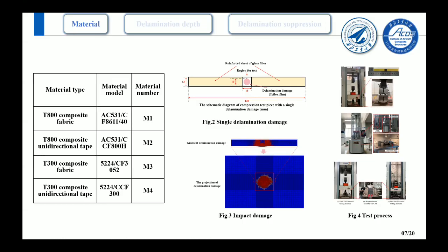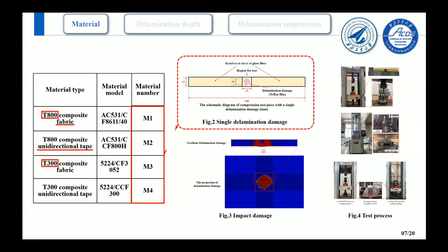For the first part of our study, we selected four distinct materials combining two strength grades and two fiber orientations, designated sequentially as M1 through M4. Delamination damage was introduced by two methods. The first involved inserting a Teflon film at the midplane during the laminate manufacturing process to create a single delamination, to simulate effects arising from production. The second method subjected the laminates to low velocity impact, replicating in-service threats such as hail, runway debris, or tool drop. It's worth noting that this phase of the research was conducted experimentally.